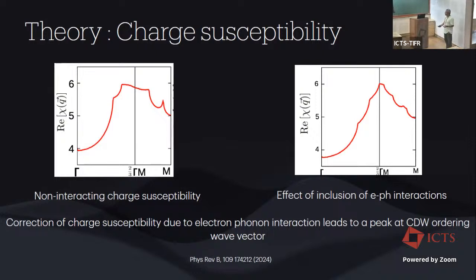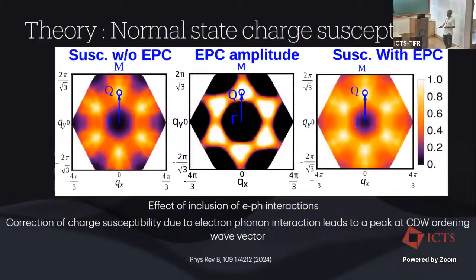So it seems that the CDW physics, at least, is being driven by electron-phonon interactions in the system, and you can see the effect of it if you calculate the electron-phonon coupling amplitude over the Brillouin zone. They are very strongly peaked at the 2/3 gamma m. That's where the renormalization of the susceptibility from the electron-phonon interaction leads to the CDW also forming at that wave